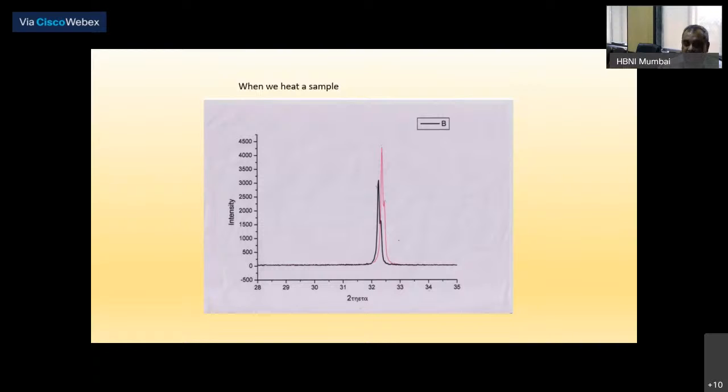It is more of an ellipsoid because the bonding of neighbors varies from one direction to another. Depending on that bonding and the strength of bond, this average displacement is not the same in all possible directions, as I showed you in my calculation, but it is anisotropic, and the more apt term will be thermal ellipsoid, and we can map this thermal ellipsoid using Bragg diffraction.